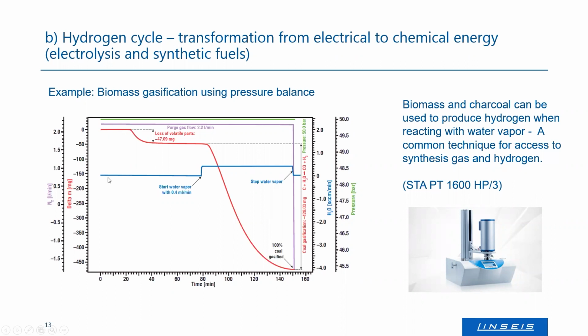You heat it up in an atmosphere where you lose all your volatile parts, and then you start feeding it with water steam, leading to an immediate mass loss. So the red curve here indicates the mass loss. You have a lot of volatiles, and once you're reaching your target temperature, you start feeding it with water, and you see the red curve decreasing. That means at that time, the carbon that's contained in your carbon-containing sample is gasified, forming carbon monoxide, forming hydrogen.